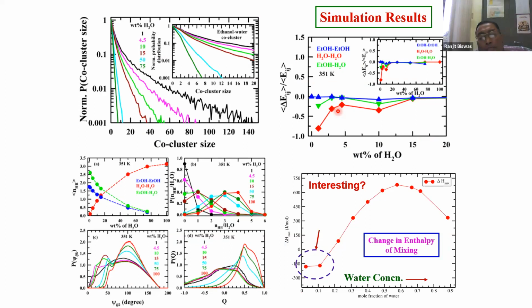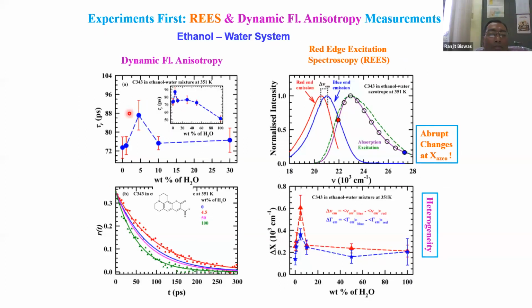Of course, anisotropy you see here, the lifetime, the rotational diffusion time is showing anomalous composition dependence, and the peak is occurring at a mole fraction of 8% water, exactly at the azeotropic composition. So at that composition you have cluster formation. The temperature we are sitting at is the azeotropic temperature. These are the experimental findings that inspired us to look at simulations. What is happening at the microscopic level? Maybe that is breaking down at higher water percentage. Could be something is happening. Definitely the friction is less here at the higher mole fraction. So definitely at the structural level something happens, and that we know for alcohol-water mixtures.